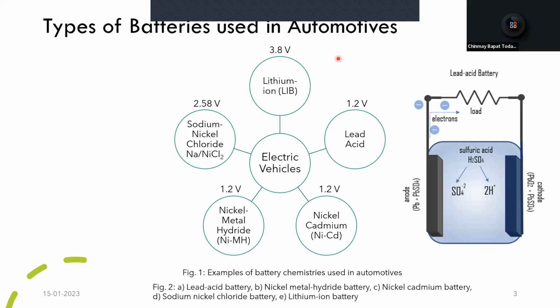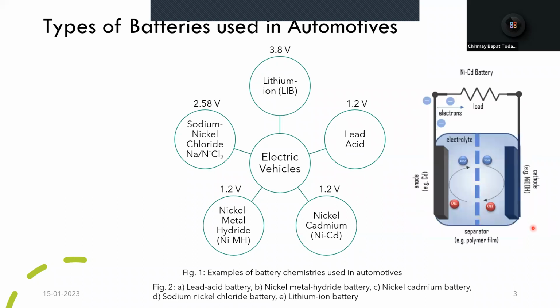So all these batteries work on the basic principle, that is during discharging, we have anodic oxidation, that is species at the anode lose their electrons. And at the cathode, we have cathodic reduction, that is species gain their electrons. So with respect to cathode, anode, and electrolyte, for the lead acid battery, we have lead oxide as the cathode and lead metal as the anode, with sulfuric acid as the electrolyte. For nickel cadmium battery, we have nickel oxyhydroxide as the cathode and cadmium metal as the anode. Cadmium is really toxic, so there have been some regulations and restrictions to the use of these batteries. And we have an alkaline electrolyte such as potassium hydroxide.